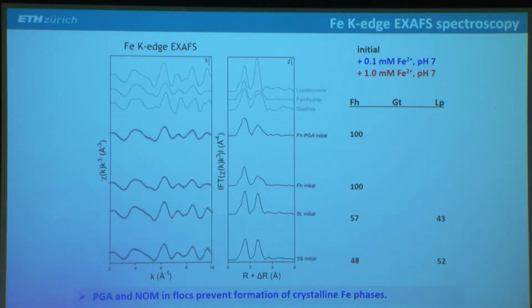So first I would like to show you the iron speciation, and let's first focus on the pure ferrihydrite, the synthetic material. This is the initial ferrihydrite spectrum, 100% ferrihydrite, and if we spike this with iron 2 at pH 7 at 0.1 and 1 millimolar concentrations, we see that we form goethite. This is goethite, this is lepidocrocite, and at the higher concentration, we completely transform this ferrihydrite to goethite and lepidocrocite. So it's completely transformed.